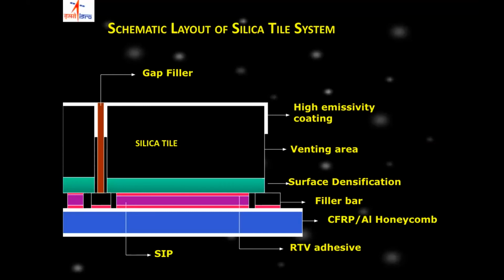So for that also, special mounting schemes having some isolation pads were developed, which took away the strains which are coming there. And finally we got successful. And here you can see the front wall temperature, these tiles were subjected to almost 1400 degrees centigrade on the front side, and they were so effective that the back side temperature was below, of the order of 150 degrees centigrade only, which is within the limit which metallic materials can withstand. So that is the effectiveness of these tiles for this application.